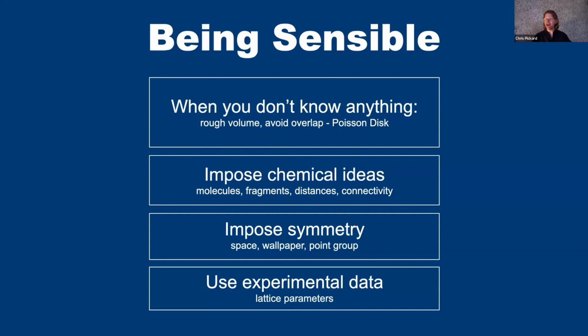That's how, as a scientist, you have a conversation with this code and you try different things. And if you put constraints that are inappropriate, you potentially can get stuck in regions of space that are not useful. Another very powerful idea practically is the use of symmetry. In many cases for crystal structures, the ground state structures have some symmetry, and this can shrink the size of the space that you have to search. You can do this in 3D or in surfaces, in slabs, or for molecules or clusters.